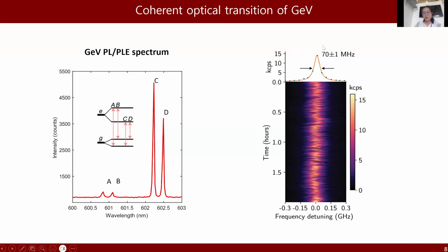For most of the time, we will observe a single narrow line that is stable on the time scale of hours. As I discussed before, an ideal atomic antenna should have a loss-free transition. In other words, it should have very good optical coherence. It should have a well-defined, long temporal profile. And if we translate that into the language of the frequency domain, it means that a good atomic optical antenna should have a very narrow optical linewidth.